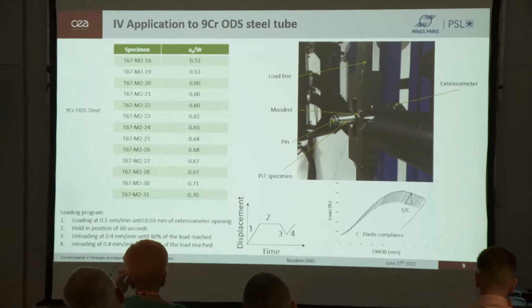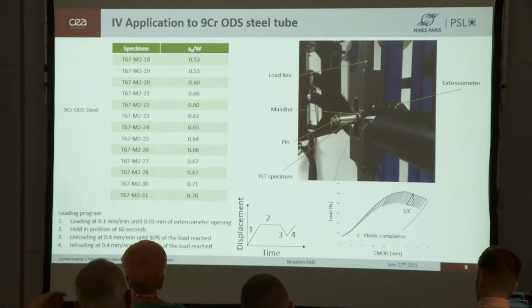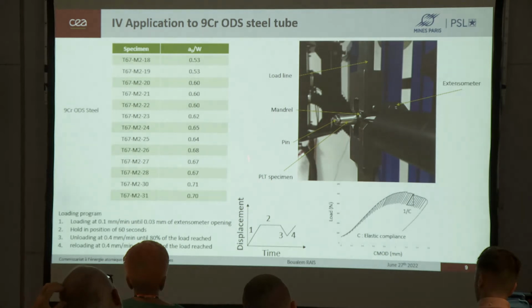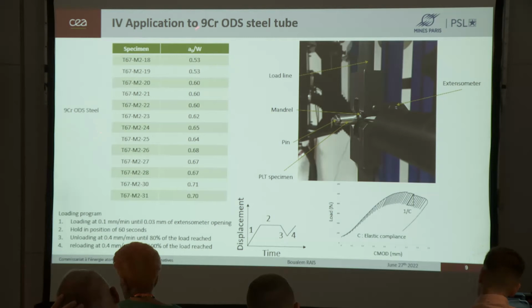So now we pass to the experimental application of this procedure. For this, we performed some tests on different specimens sampled on a 9Cr ODS steel tube. The different crack lengths tested are referenced in this table. The loading program consists of cycles of load, hold, unload, and reload every 30 micrometers of CMOD. And the CMOD is measured by an extensometer, as you can see in this picture.